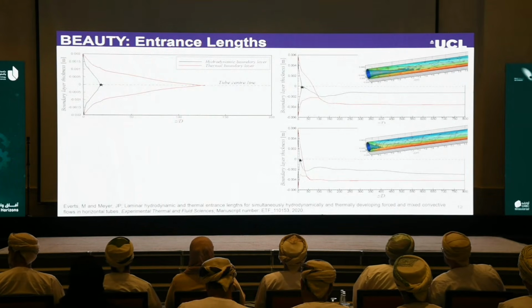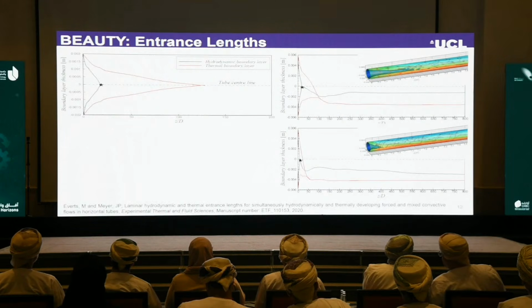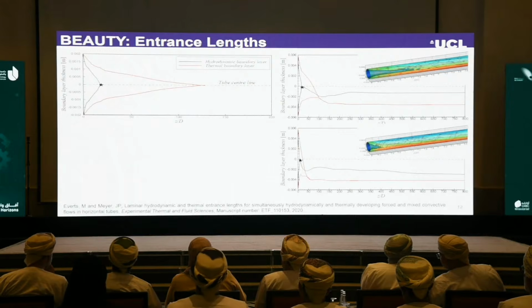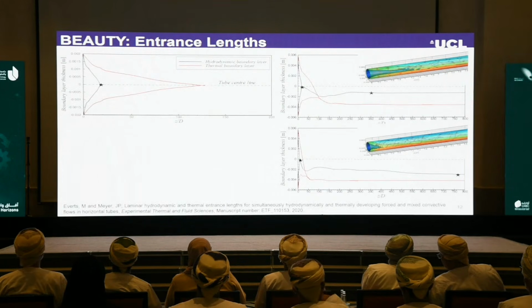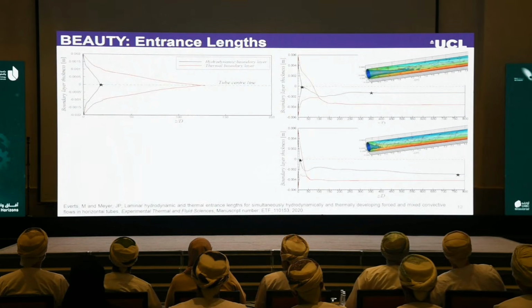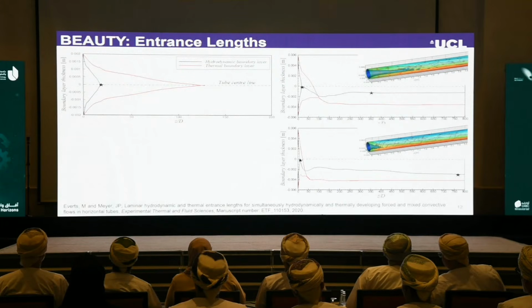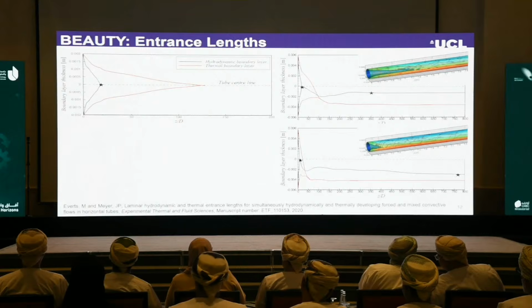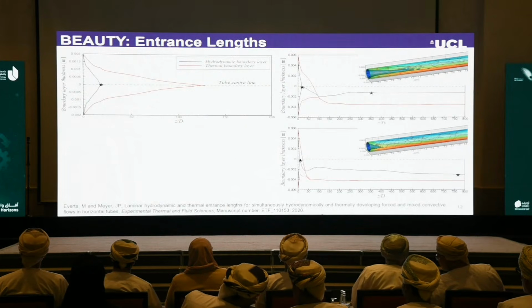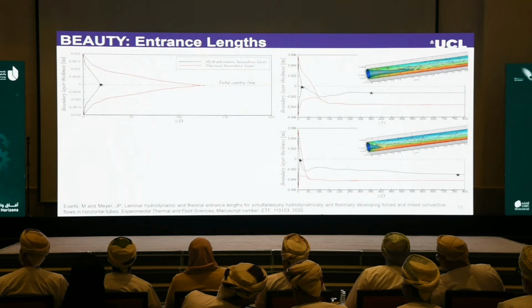So if we start with the hydrodynamic boundary layer, which is the black lines in this case, we see that for both forced convection and mixed convection, it merges in the center of the tube. However, when we increase the mixed convective conditions, this point occurs earlier inside the tube. But then the big difference is that this point does not stay constant. It actually decreases, increases slightly, and only then becomes constant, and thus fully developed, much, much later along the length. So what this tells us is that this mixed convective behavior, which is really favorable from a thermal perspective in terms of mixing, is actually disturbing the flow development and delaying the flow from becoming hydrodynamically fully developed. And we need to pay a price for that, which is increased friction factors, pressure drop, and thus pumping power.